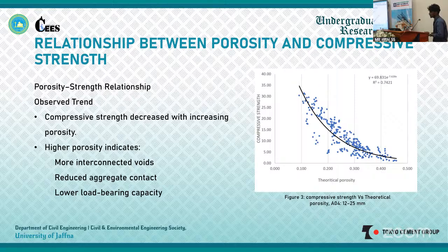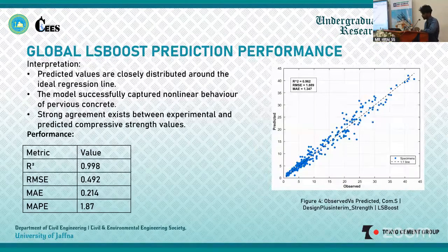This slide shows the results of the LSBoost model. This is the best model. The model gave very accurate predictions. It achieved an R-squared value of 0.998, an RMSE value of 0.492, an MAE value of 0.214, and a MAPE value of 1.87. And the predicted values are close to the experimental values. This shows the model can predict the compressive strength very well.